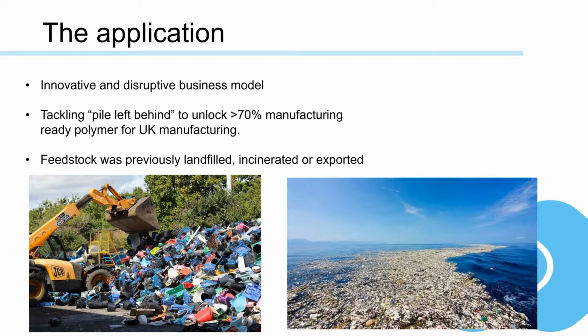But when we got it working, and we were able to separate to pure polypropylene, pure polyethylene, and pure PET, we realized that the technology could do a whole lot more than just plug into a single source mechanical recycling supply chain. So we looked at what was going to incineration and landfill, and of course this is now what we do in Newcastle. By making this stream worth something, we are paying for this material, or we take it in for zero, when in fact it has a negative trading value. By taking this in, we prevent it from being exported to countries with poorer waste regulations, and ultimately prevent it going into the ocean.